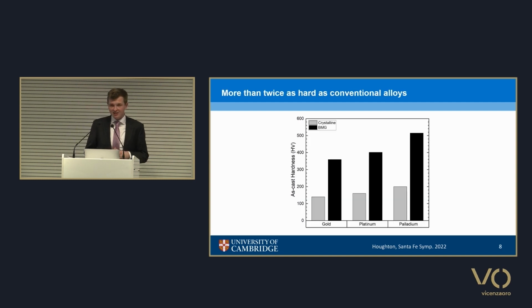One of the main advantages of BMGs is their hardness. So here we've got a chart of different metals and the crystalline alloy and a BMG of comparable fineness. And as you'll see, the hardness is typically at least twice as high. And this is due to their atomic structure. Whereas in a crystal we have layers of atoms that can slide easily over one another, they don't exist in the glass. And so glass is actually deformed by a mechanism of shear band, which I won't go into. But ultimately it means we have very high elastic strains under large loads. And so we don't see macroscopic ductility in the same amount, but we do have much higher hardness.